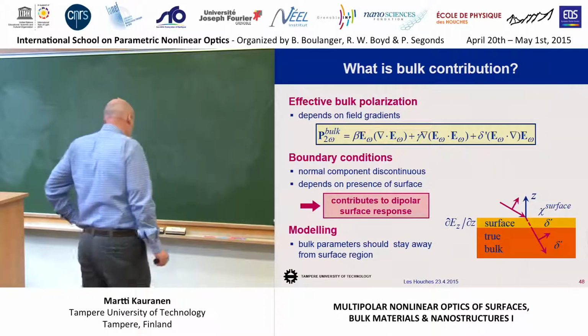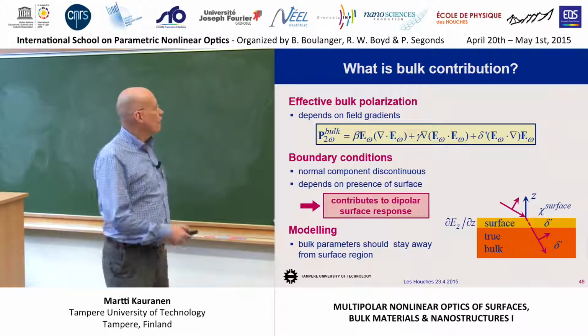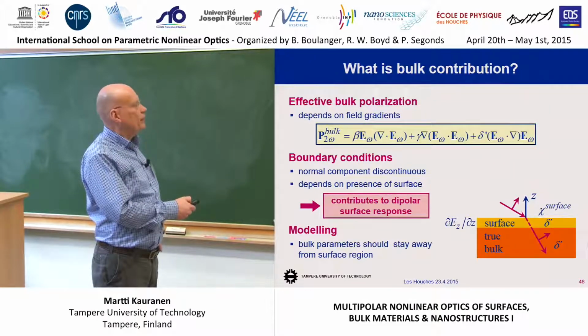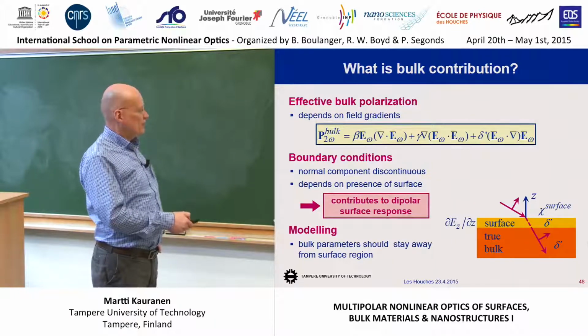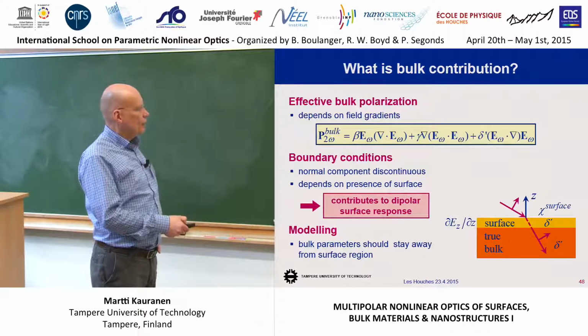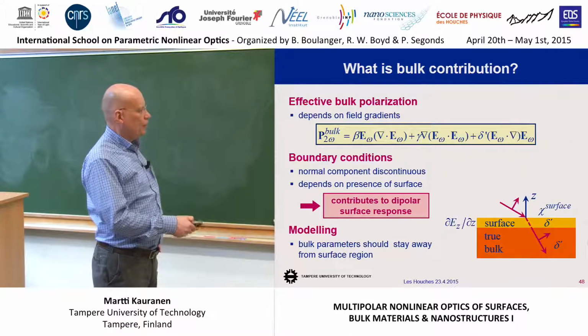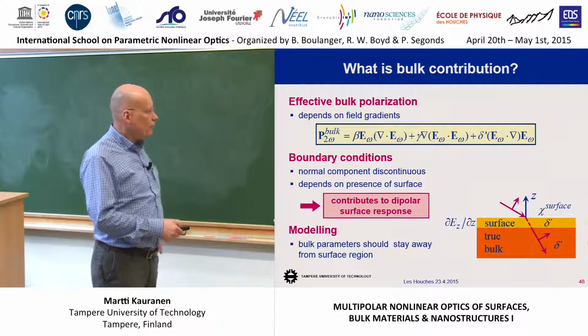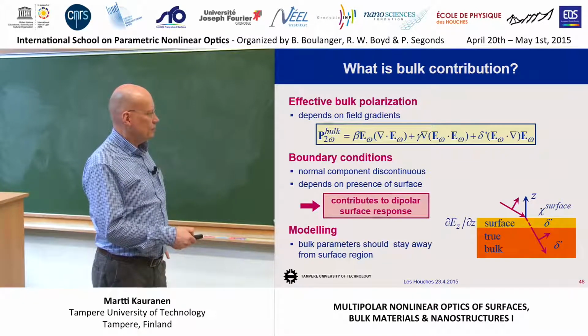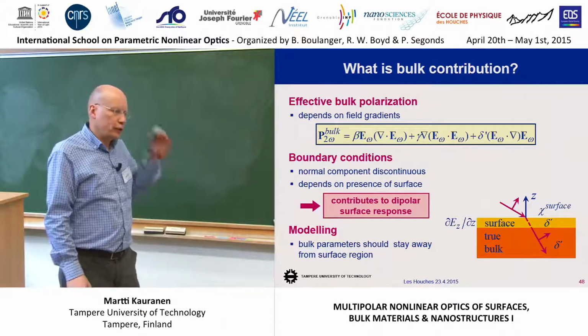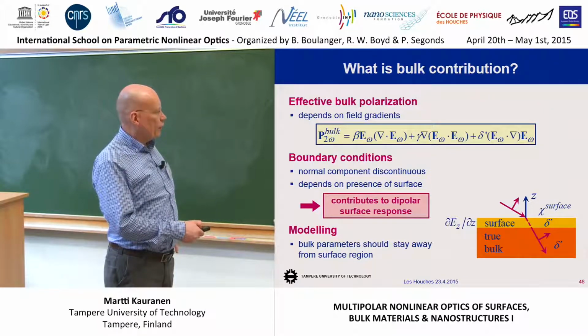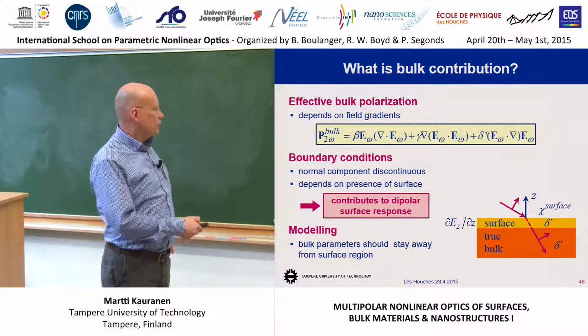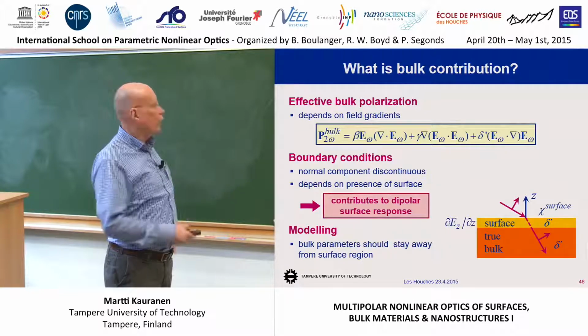Another problem: what do we mean by the bulk contribution? The bulk effects, or in general these higher multipole effects, depend on field gradients, right? When you come to an interface between two media, the Z component of the field is discontinuous. You have a well-defined value in the bulk medium here, in what I call true bulk. And then something happens at the surface layer, which has a thickness of maybe a few atomic layers. Because the Z component has different values here and here, there's a really strong surface gradient. If you take this surface gradient into account in this expression, you are going to get a really strong response, right?